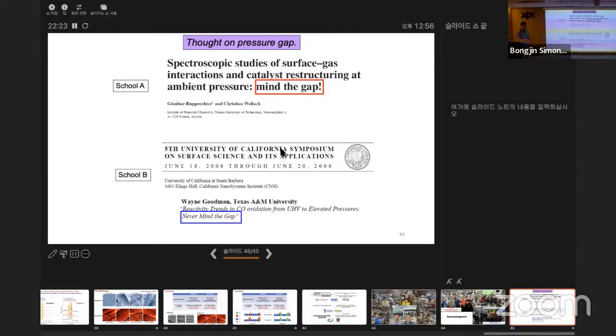And so with the help of the STM, we start to see some evidence, maybe partial evidence, not direct evidence, but we start to see some changes due to this elevated pressure, and that happens mostly at the steps, not the terrace so much. I mean, always, the step is the first to get oxidized or form clusters, and then the atoms start moving away, or sometimes the terrace actually takes over too. But we already see the step is where the action takes place, the place where oxygen can easily go in and pull the transition metal underneath.